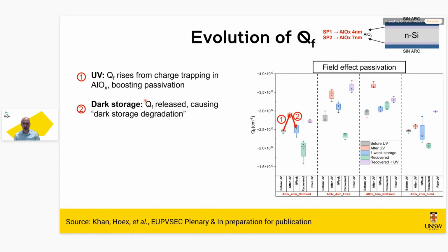In dark storage, this charge actually is released back. So in the dark, the additional charge you pump into the system is released. And this is something we also already showed in 2008. So it's not really new for us. But you see consistently that you pump it up, it leaks out, and that is the main cause for this dark storage.